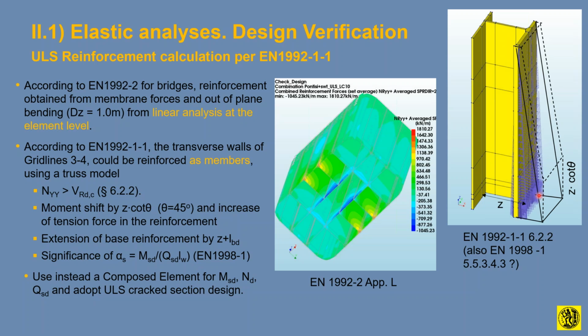And in fact, what really happens is that the critical rebar, the fixity of this cantilever, has to be, in fact, extended over a full effective depth here, zeta, where the lever arm is practically the full width of this panel here, and then plus a development length. So one should anchor these fixed reinforcements here in order to accept the 45-degree crack, which is going to happen once this guy cracks under the lateral forces during the installation phase, which moves the tensile forces at this level here.